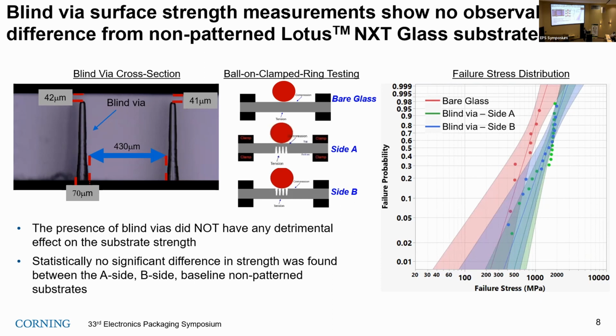You can see that even though there is a slight shift between the two distributions, bare glass versus blind via, their 95% confidence intervals overlap each other. So we see no significant difference in the strength between the A side and B side and the baseline non-patterned substrates. Having a blind via is not detrimental to the substrate strength of the panel.